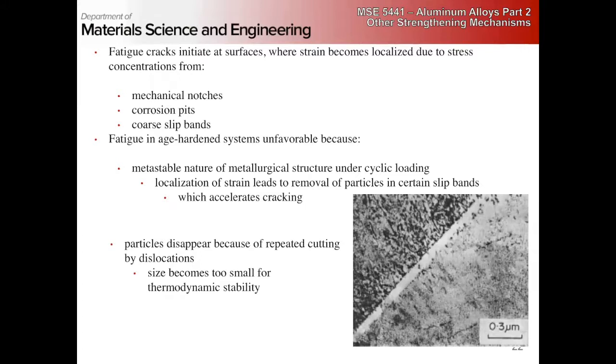So as I was saying, fatigue cracks initiate at the surface where the strain becomes localized due to stress concentrations, right? So what are the sources of stress concentrations that we have to be concerned about? Well, mechanical notches, right? Anything, gouges, scratches at the surface, anything that's going to cause stress to be concentrated,